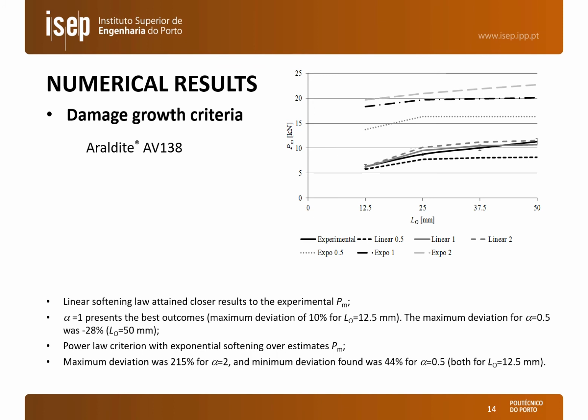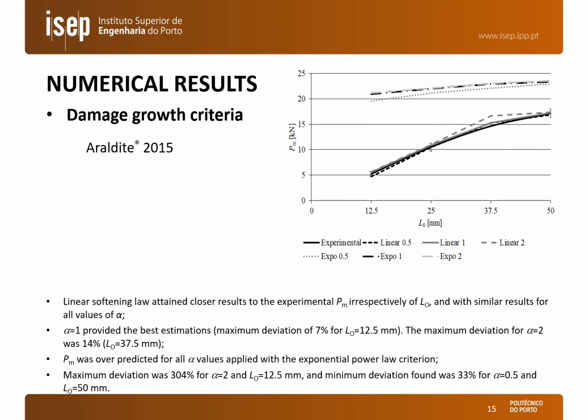The power law criteria with exponential softening was found not to be suited for this case because it highly overestimates the maximum load. The same results for the 2015. Here we can see that the linear damage propagation laws behave almost identically, irrespectively of the exponent. The best results nonetheless were found for an exponent of 1 with a maximum deviation of 7% for an overlap length of 12.5 millimeters, and the maximum deviation for an exponent of 2 was up to 14%, but nonetheless the results are more or less similar. And once again, the exponential criteria showed not to be suited to model the behavior of these adhesives.